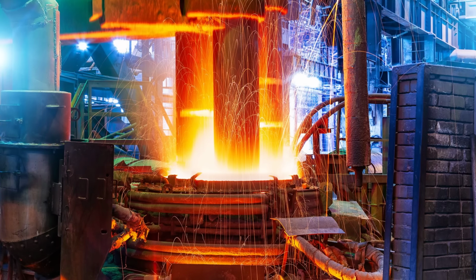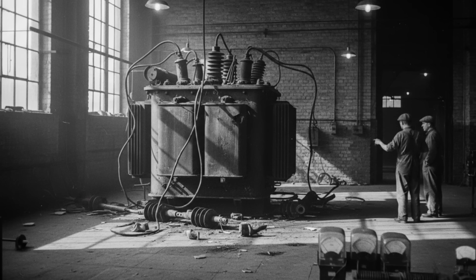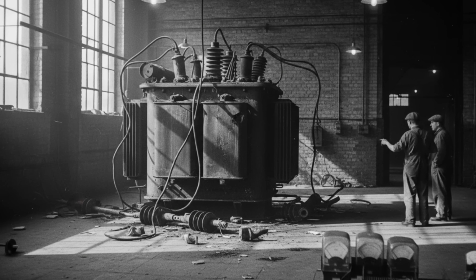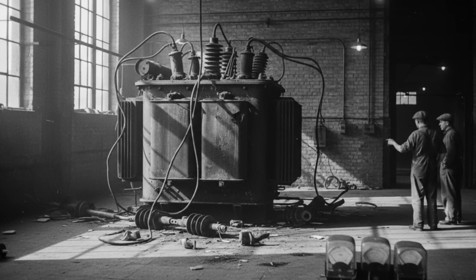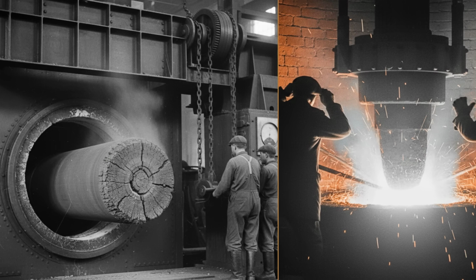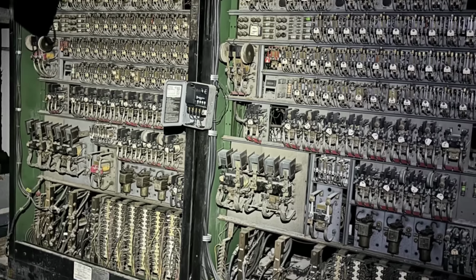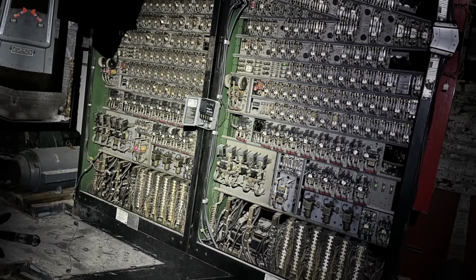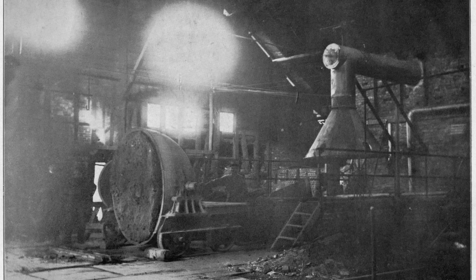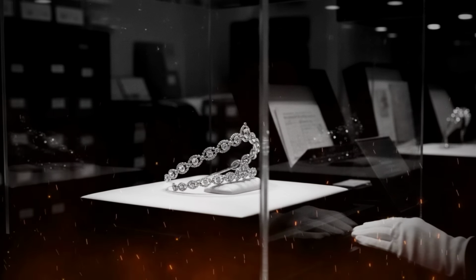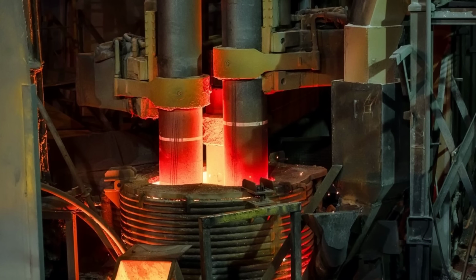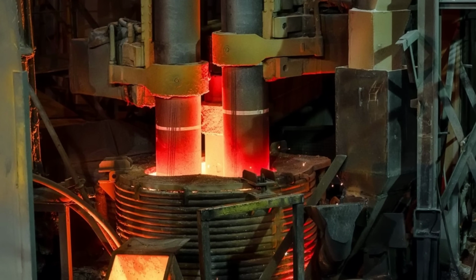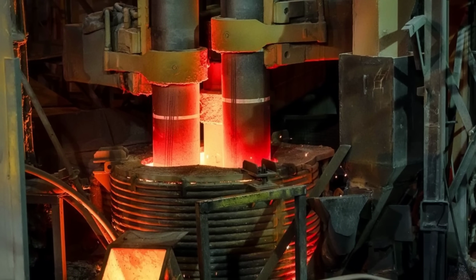Too close, and the arc would short against the steel, flooding the circuit with uncontrolled current and potentially destroying the transformer. Too far, and the arc would extinguish, requiring a restrike that sent a voltage surge through the entire electrical system. The regulation system had to hold that gap through an entire heat lasting several hours, compensating continuously for the electrode tip burning away as the arc consumed the carbon, and for the steel charge level rising as solid scrap melted into the liquid bath below.